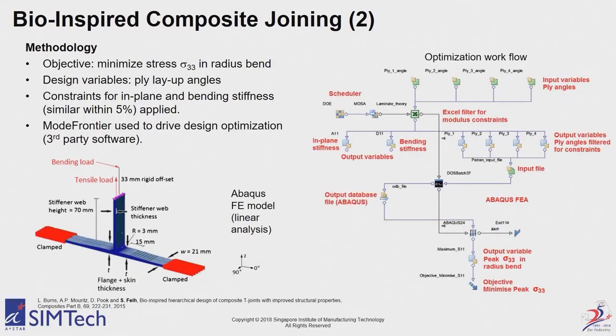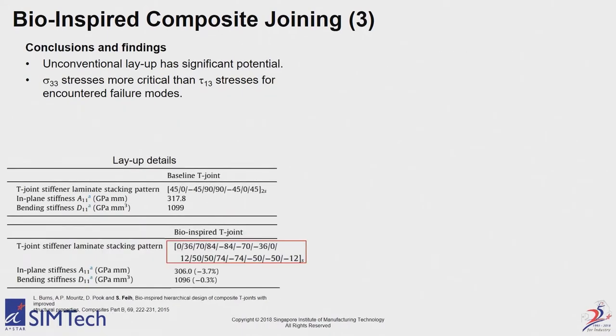Then we thought, okay, this is not enough. We actually need to, like the tree, optimize our layup as well. Again, this is not something we could easily do experimentally. So this is where simulation comes in. And at that point, we didn't have Isight, so we used modeFRONTIER, but that doesn't matter. It's the same kind of task, where we actually look to optimize the different ply angles to give us minimal through thickness stresses. And therefore, that was the hypothesis, we would get a better strength of the joint. And that, in fact, did happen.